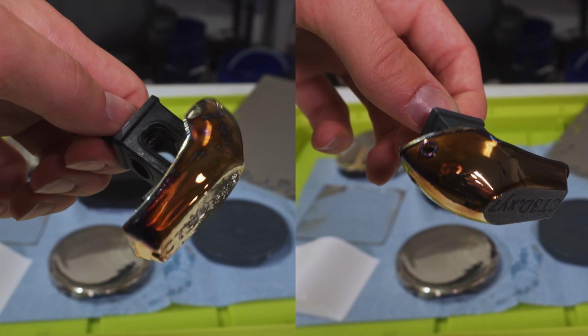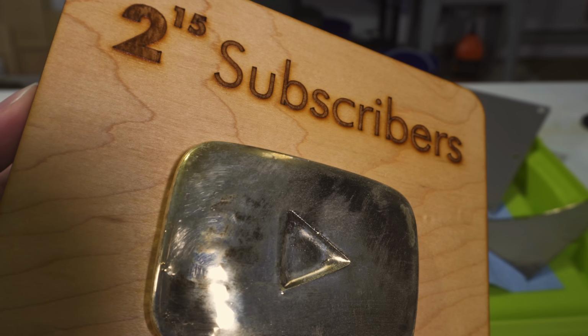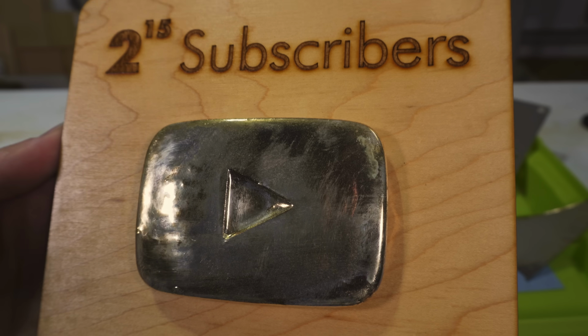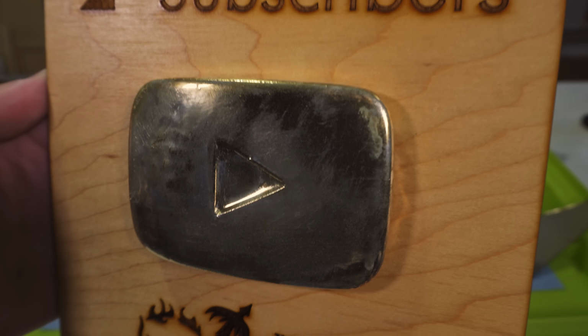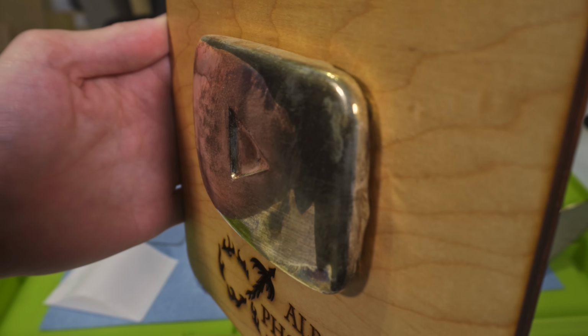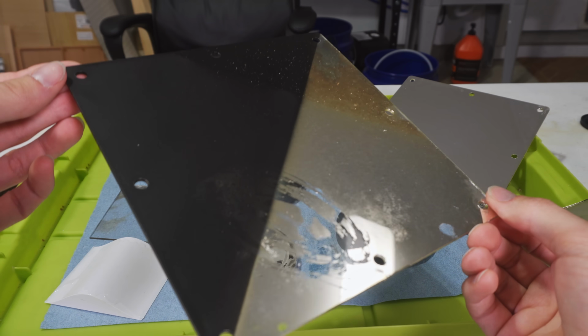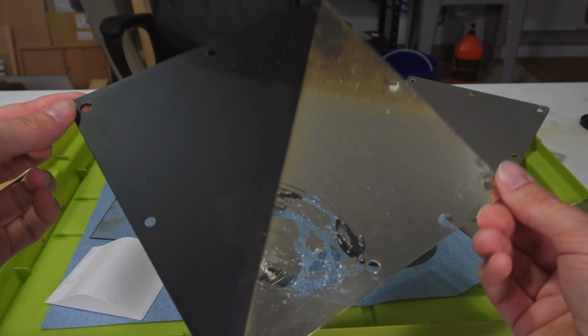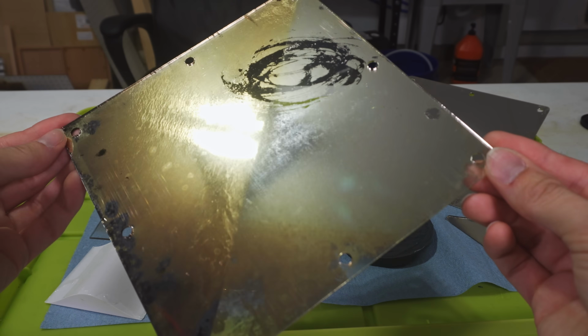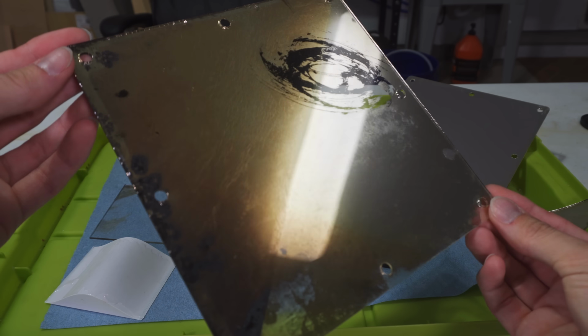I think the reason behind the patchiness is due to inconsistent mixing of the resin that I used underneath the metal layer. One of the mirrors I made more recently, I tried to cover up the backside of the silver with various spray paints, and the aging was almost instantaneous and different with each coating. So if you cover up the silver, you've got to use something that is designed to form a solid coating without reacting with the metal. Otherwise, it's gonna end up like this.